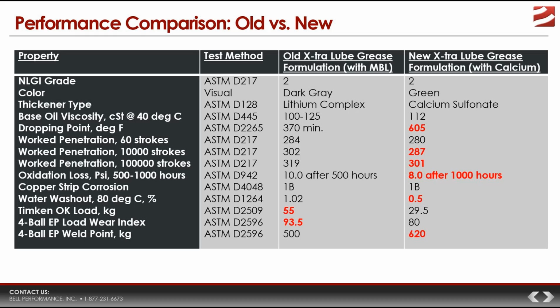Since it's made with a lithium complex grease, we know from a grease chemistry standpoint that lithium greases top out with their dropping points at around 500 degrees. And that is a standard property of lithium greases. You cannot have a lithium grease that has a dropping point that is significantly above, let's say, the low 500s, maybe 525, somewhere between 500 and 525.